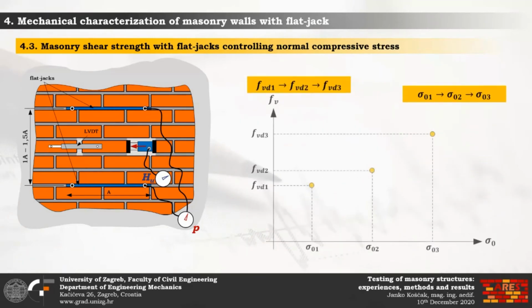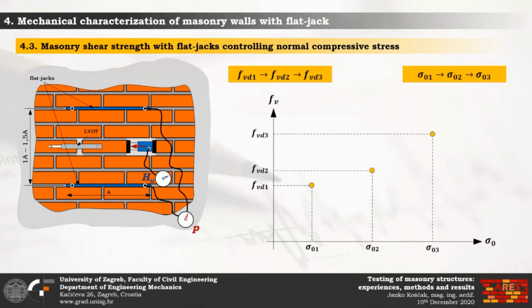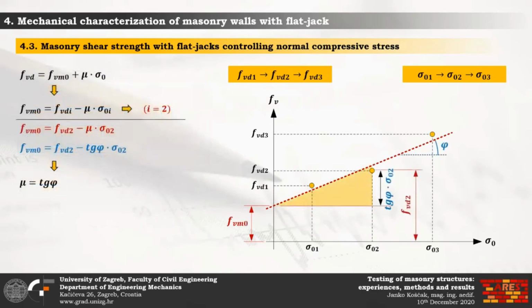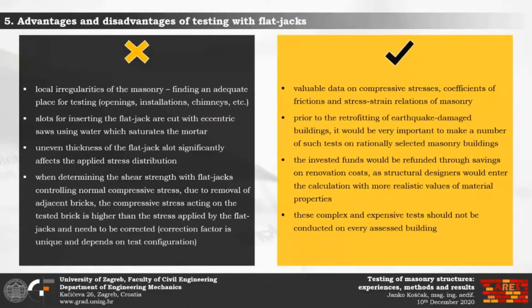We can now plot the values of FVD on a vertical axis against the values of normal pressure on the horizontal axis, and the best fit straight line is plotted through the given points. This is the red line on the figure. The intersection of this line with the vertical axis represents the pure joint shear strength at zero normal compressive stress. This is FVD0. Finally, it is clear from the figure that the inclination of the best fit line represents the friction coefficient.